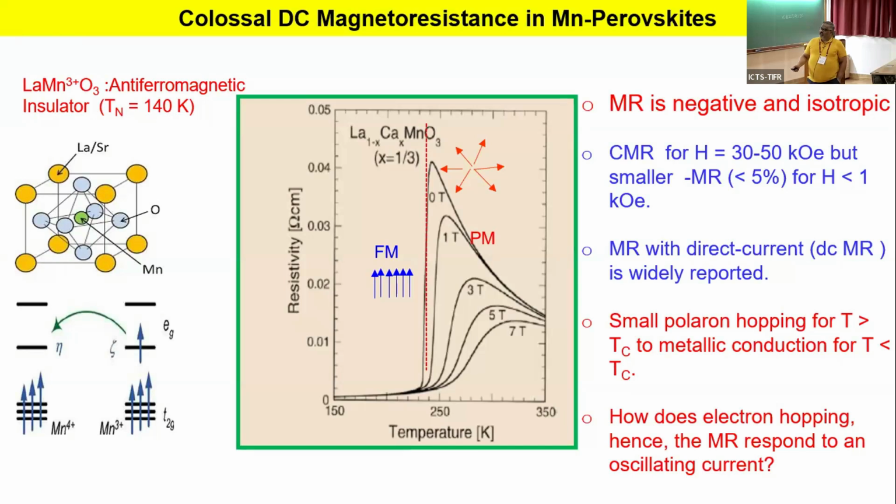So ferromagnetism promotes itinerant electronic behavior. If they are disordered, then electron hopping is reduced, and it can show a semiconducting-like behavior. So that is the basic principle. The mechanism is the Zener double exchange mechanism, which drives ferromagnetism in this compound. As you can see here, this is the normal resistivity behavior of these doped manganites. A semiconducting-like behavior in the paramagnetic state, and then a sudden decrease in the resistivity when ferromagnetism sets in. So you have a peak in the resistivity close to TC.